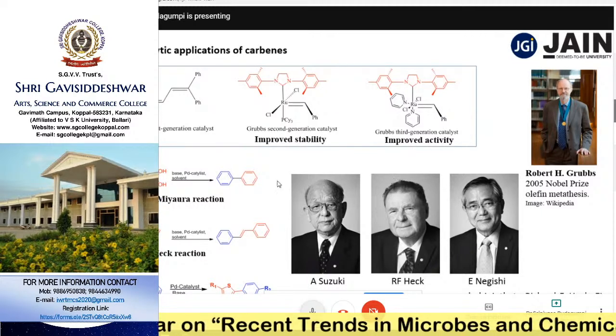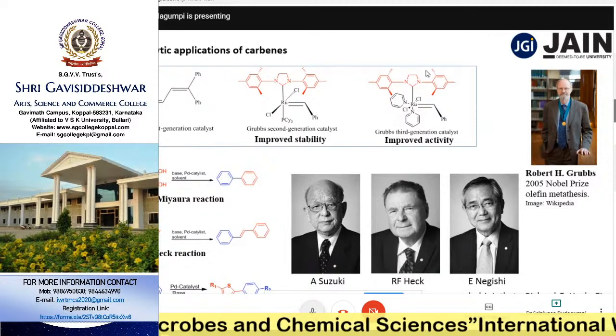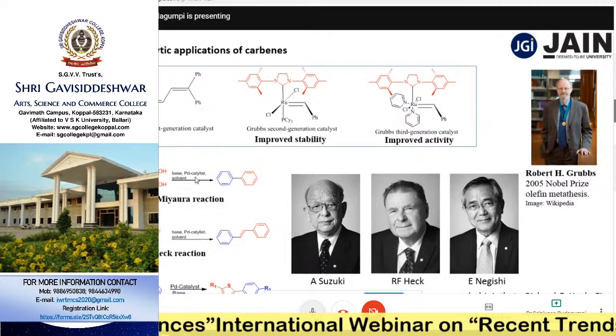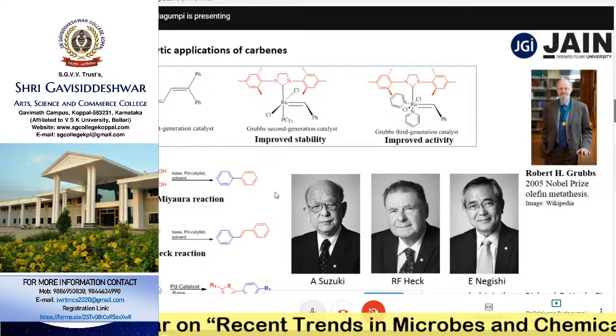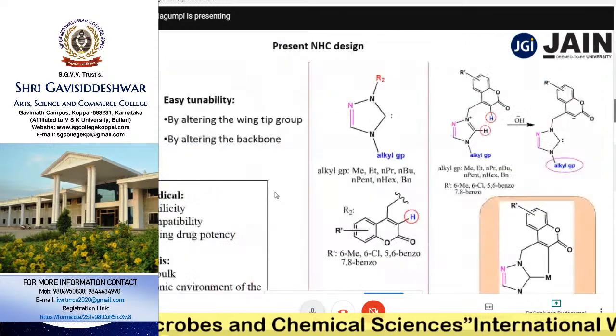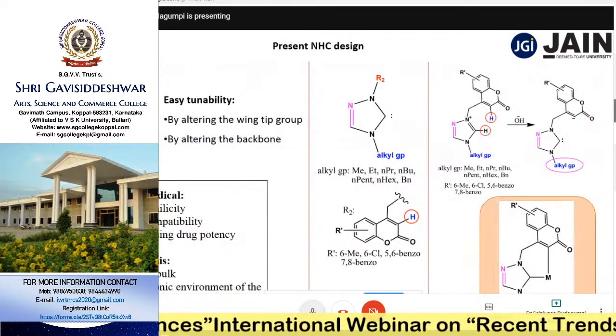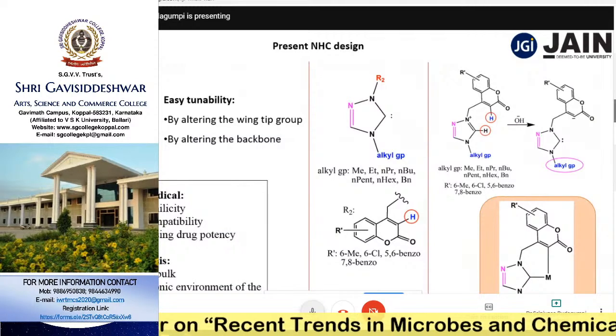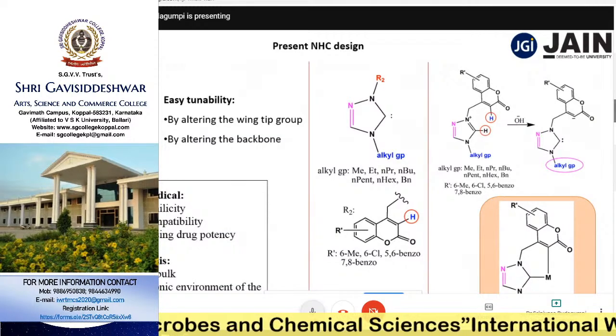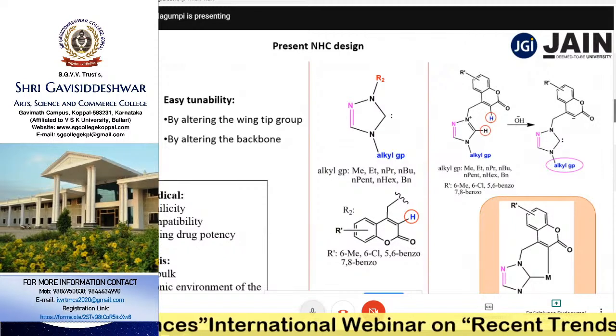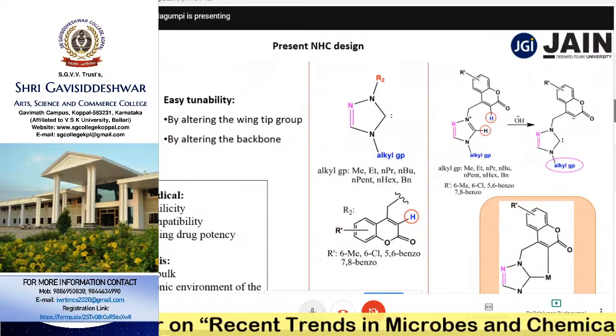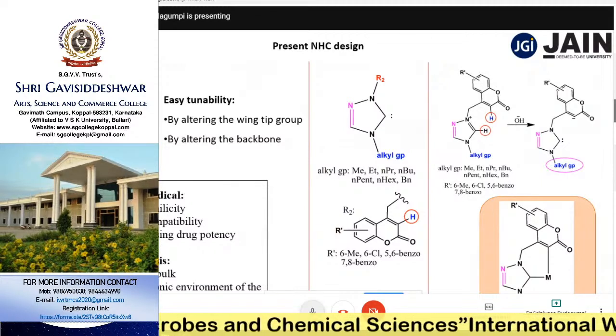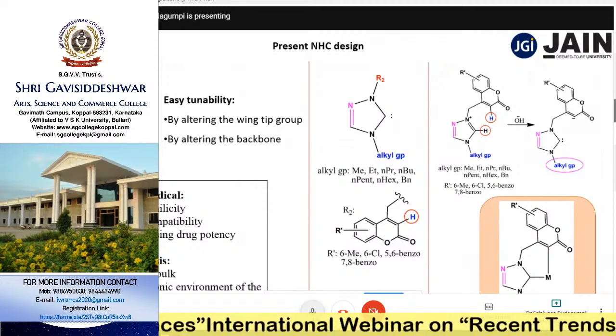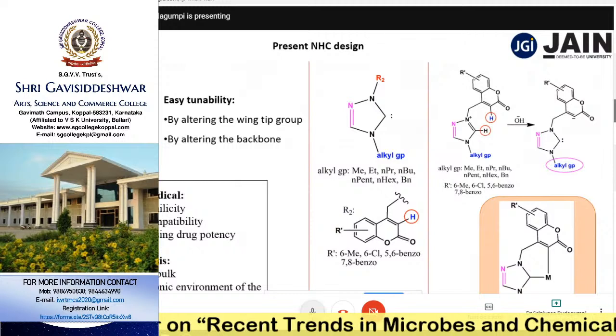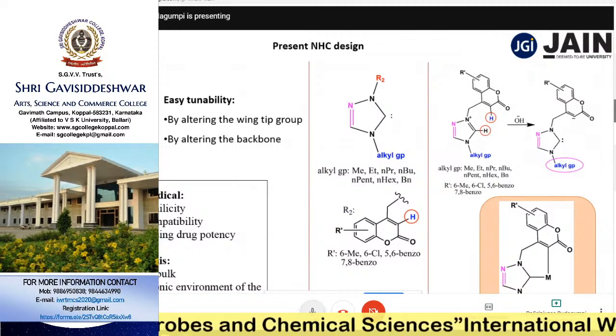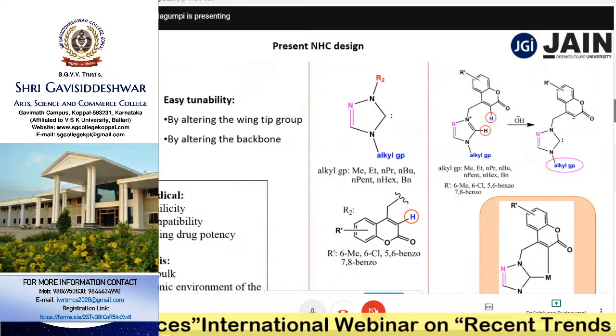Now, my research work is a combination of these two things. We have the NHC stabilization from the Grubbs catalyst, and the palladium source is an active catalyst for C-C coupling reactions, right? So on these grounds, we have designed our ligand systems. Why are NHCs given more focus or prominence in our ligand system? Because the R substitutions, R1 and R2, on the nitrogen atom can be fine-tuned. We call them wingtip substituents, and these wingtip substituents can be donor functionalized, with the help of a donor atom which can coordinate to the metal center in order to increase the stability of the compound. So these NHCs can be fine-tuned at the nitrogen atoms to meet the steric and electronic requirements around the metal center in the complex form.